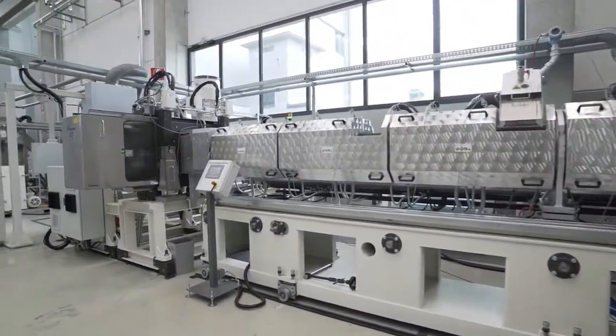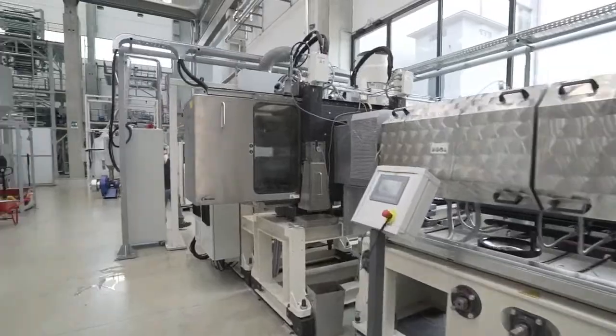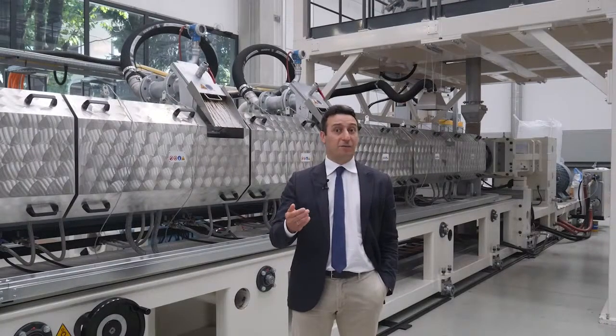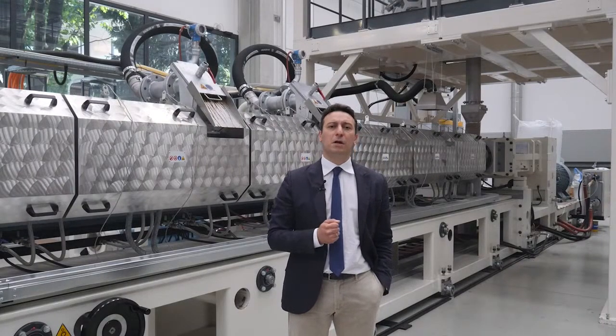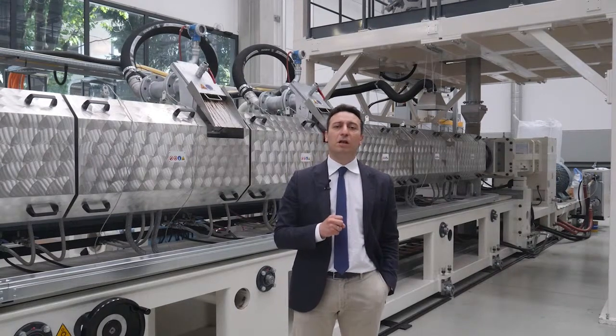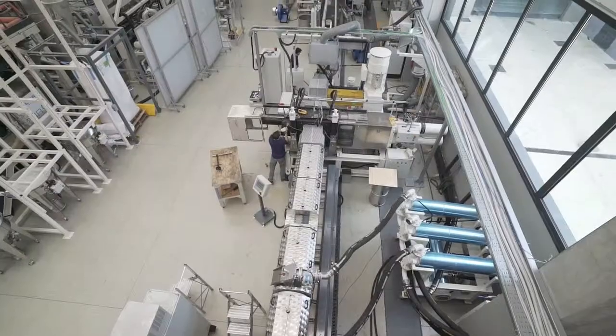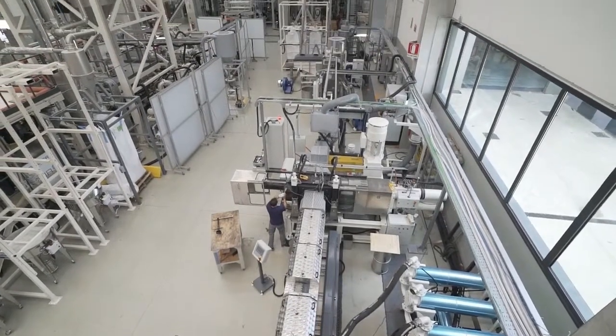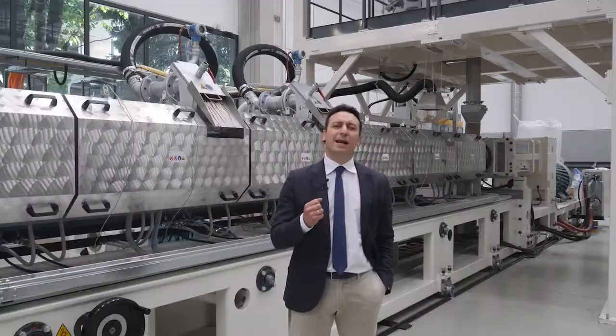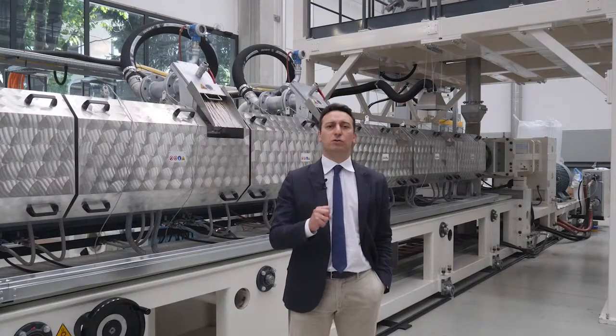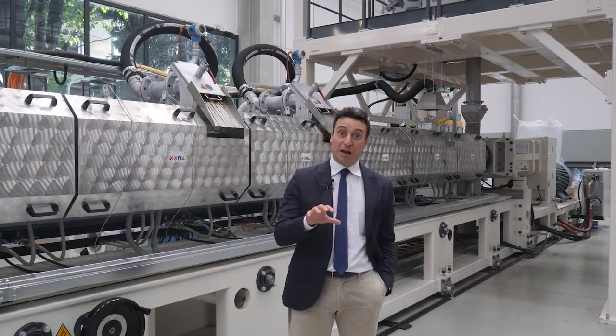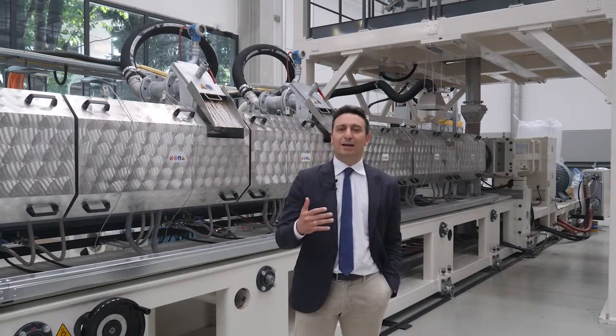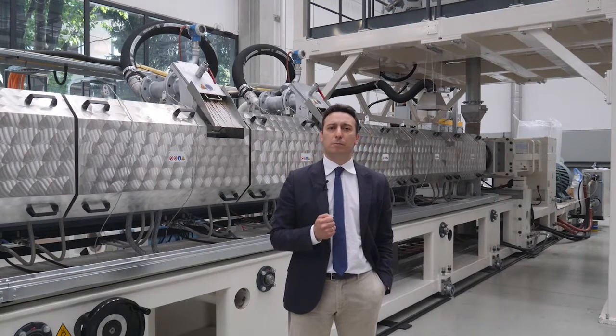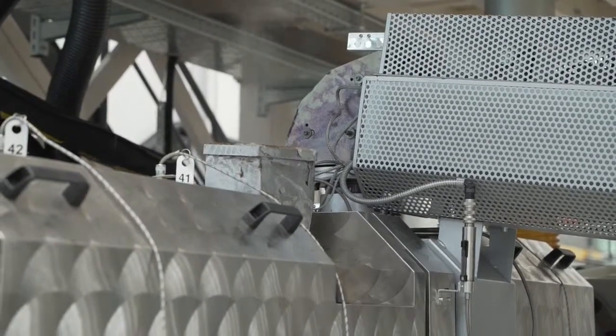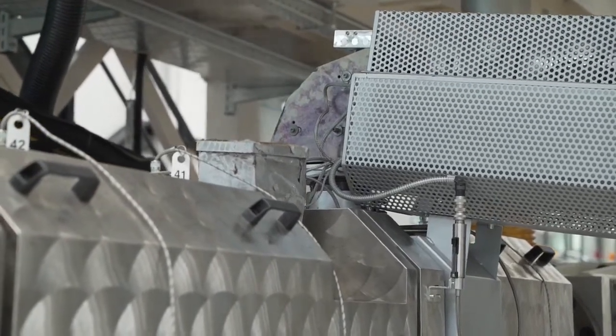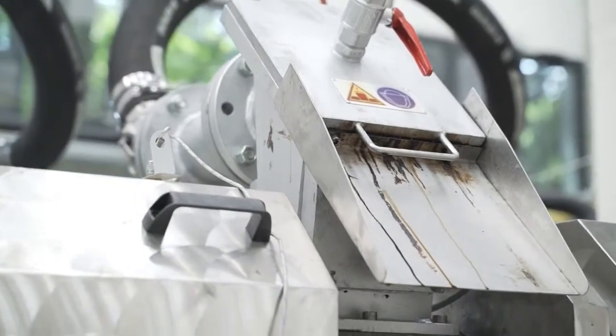is fed into the secondary co-rotating twin screw, where additional materials such as mineral fillers, glass fibers, resins or other additives can be blended together for fulfilling specific customers' needs. The secondary twin-screw extruder performs an additional degassing stage for the extraction of the VOC generated by the previous filtration, in which solid contaminants, such as paper and wood, can burn and generate undesired subproducts. Moreover, the two-stage degassing process dramatically reduces ink and solvent contents.